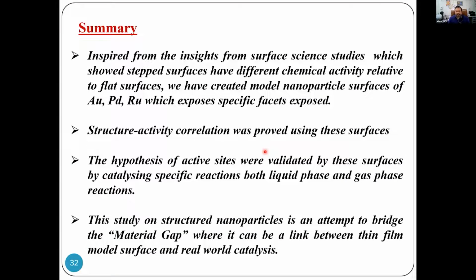Right, so summary from these last 15-20 minutes, what I was telling you was a lot of insights have been taken from surface science studies, looking at the stepped single crystal surfaces and trying to look at the activity correlation on nanoparticle surfaces of gold and palladium. Ruthenium I did not talk about in this particular session. These expose certain facets, and structure-activity correlation has been provided. And this hypothesis of active sites is validated by the surfaces by catalyzing these specific reactions, both in liquid phase as well as gas phase.